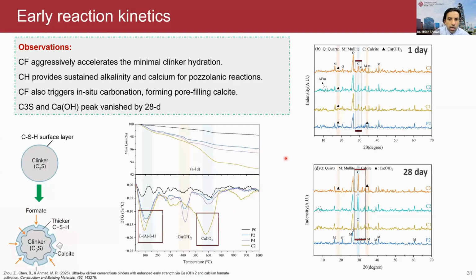The third and last phenomenon we observed is that there's a high volume of calcium carbonate. Otherwise, we can say in situ carbonation, which forms very tiny calcite particles that can fill the pores and densify the microstructure. We saw these observations with the help of TGA and also XRD. If you can see here at 28 days, as compared to this control mixture, there's a huge increase in the intensity of the calcite mineral.